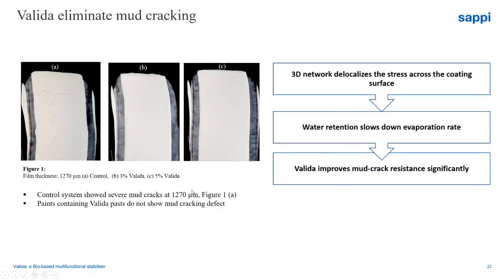Another common challenge occurring in waterborne coating is mud cracking, which is peculiar of very thick coating layers, as we can see here. The first picture on the left, I hope you can see, shows severe cracks onto the surface of the layer. When adding Valida already from 3% of the paste grade, those cracks start to disappear until completely disappearing when adding 5% of the Valida paste. And why does this happen? Well, this is basically due to the synergy between two different features of Valida: the water retention and the 3D network.